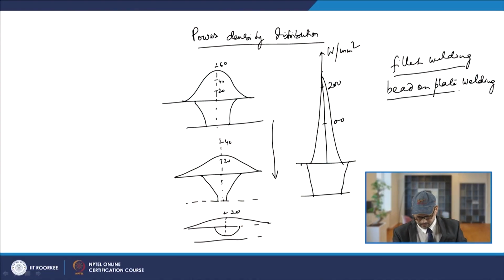So, if you take the two cases, and if you have the same heat input and for the same thickness, the cooling time will be shorter for the fillet welding as compared to the bead on plate welding, because of the greater heat sink in the fillet welding. So, that is the difference, the different type of heat sink effect.